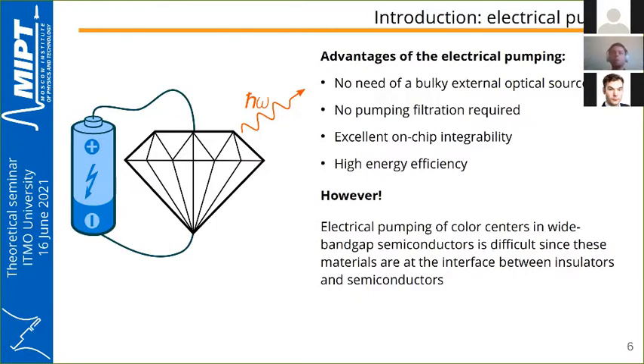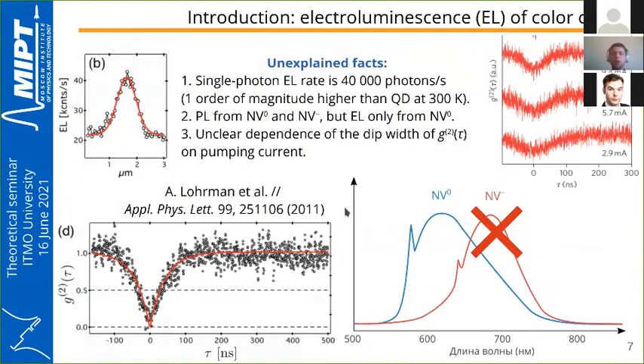However, electrical pumping of color centers in wide bandgap semiconductors is difficult, since these materials are at the interface between insulators and semiconductors. This led to the fact that the first work on single-photon electroluminescence of color centers appeared only 10 years ago, and the results under electrical pumping were different from those under optical pumping. For example, the brightness of the defects under electrical pumping was one order of magnitude lower than under optical pumping.